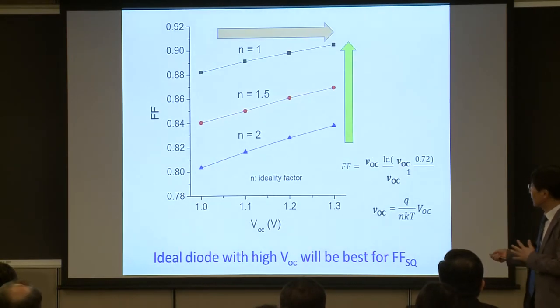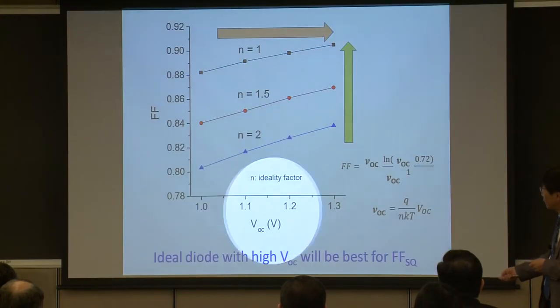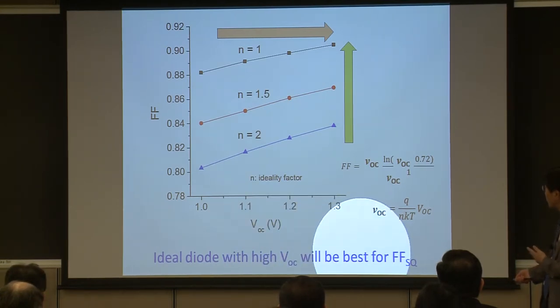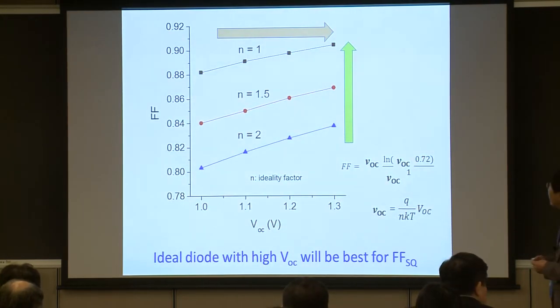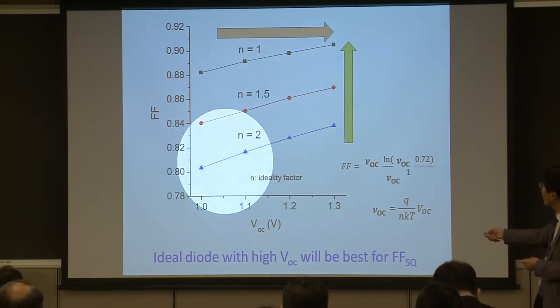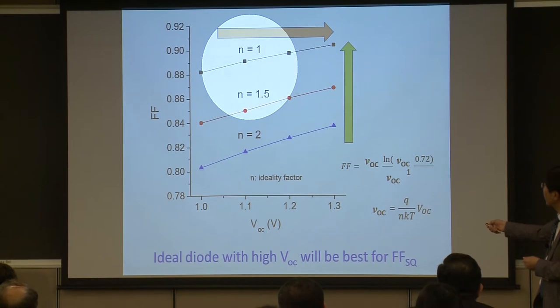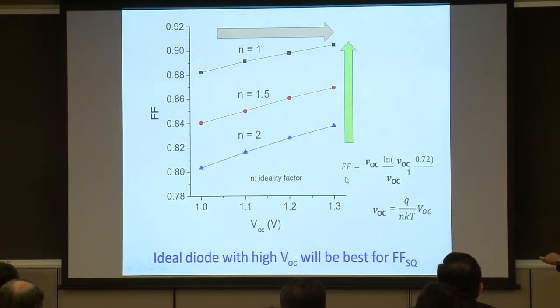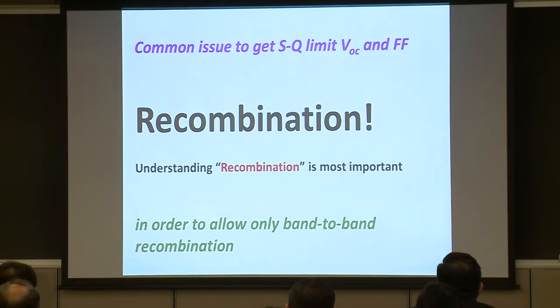And then there is some relationship. In order to increase the open circuit voltage and fill factor, probably you need some ideal diode with high open circuit voltage, which can produce the Shockley-Queisser equation fill factor. For instance, the ideality factor here, you have to improve. If you approach the ideal diode structure, then you can increase the fill factor, and also when you increase the open circuit voltage, you can again increase the fill factor. So the common issue to get the high open circuit voltage and fill factor is the recombination issue. So the better understanding of recombination is very important to achieve the Shockley-Queisser equation limit of the perovskite solar cell.